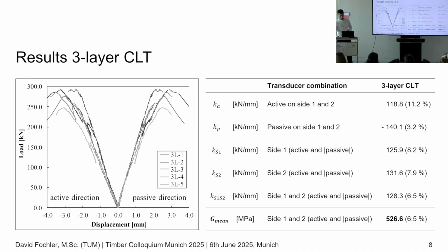And when we look at this figure, we can see the active direction, so this is the force and the vertical displacement. We see that the displacement is slightly higher than in the passive direction, resulting in a lower stiffness in active than in passive direction. Overall, a shear modulus of 526.6 megapascals was measured with those elements. How we have to evaluate this comes later in the conclusion.